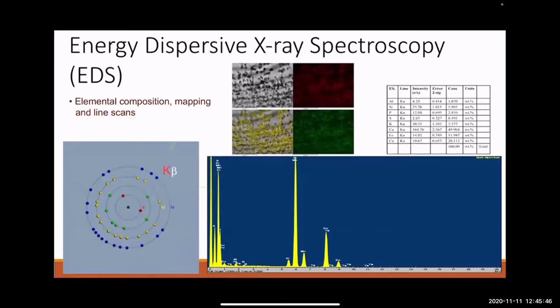So if you were to have an X-ray detector and you detected this X-ray coming off and measured its energy, then you could determine what atom you interacted with. So basically it's an elemental identification technique. And so you get a spectra that looks like this. You can see here's a chrome peak, copper, tantalum peak. It allows you to understand a little bit of the chemistry, if you will, of what's in your material, and you can map for it too.